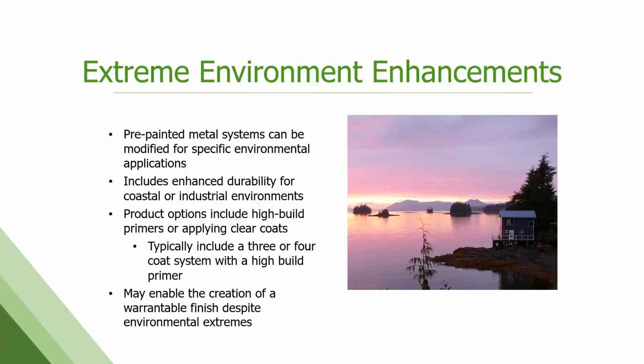So there are special high build primers with extra corrosion protection. Then you put your regular top coat down, but then they almost always have a clear coat on top as well to help give them that extra layer of corrosion protection long term. So it's typically a 3 or 4 coat system, which means it has to go back through the paint line twice. So there's a little bit of added cost and time to get those done. But it is a warrantable finish. It may not be as long as a, quote, normal location, but there are warranties available for that.